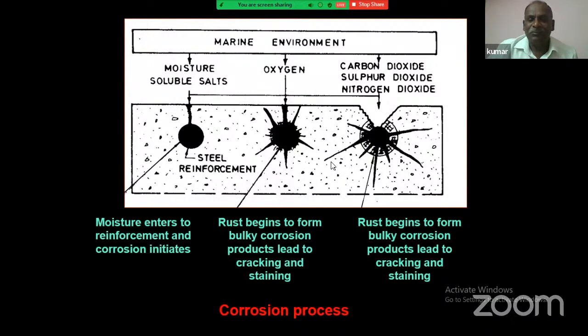You see, in normal concrete, if it is in the marine environment, or in any other environment, wherever chloride or any other salts are coming in, then these are the problems. Because of the moisture, the moisture-soluble salts, that means chloride or sulfates, sulfates also do the same process, are penetrating inside. I said already, moisture automatically makes a balancing effect. So it is attaching on the dried concrete and going in. That is the path it creates. Then automatically the salts also penetrate to the steel surface and it starts corroding.